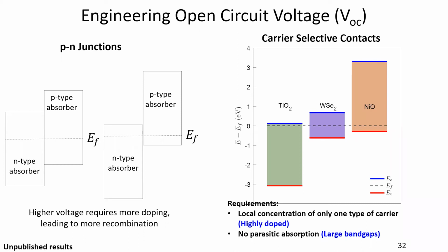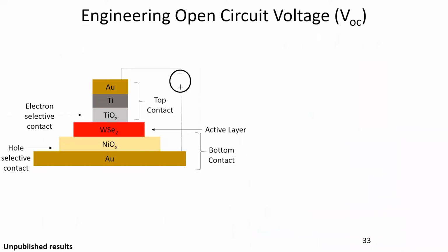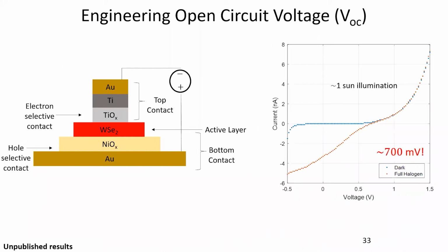There is more room for improvement over here, but we have seen that, to some degree, TiO2 as an N contact and NiO as a P contact are useful with WSe2. If you make a device like this, we have seen in preliminary data that the open circuit voltage can go up to 700 millivolts. Now, this is, of course, close to the open circuit voltages of silicon solar cells, so this is very promising. Also, if the band gap is 1300 millivolts, 700 millivolts is more than 50% of the way there. So we feel very good about it.